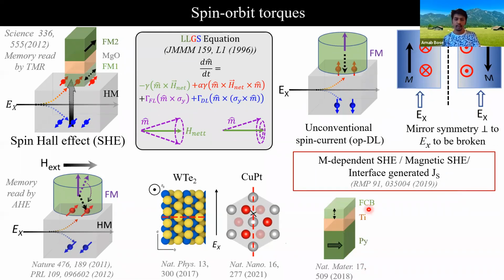In one case, we have this sort of magnetic trilayer. We have an in-plane magnet and an out-of-plane magnet separated by a non-magnetic spacer. So this in-plane magnet is the source of spin current, and this is the detector. When we run the current, it creates out-of-plane spins that produce an out-of-plane antidamping torque on the perpendicular magnet. This has been reported in this work.